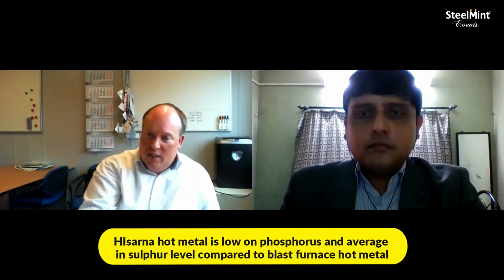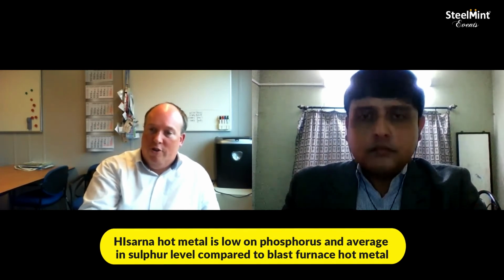Well, the HIsarna process as such supplies a hot metal that is not dissimilar to a blast furnace hot metal. It's got the main components in there, but it's slightly lower in carbon, about 4%. It's got virtually no silicon. It is low in phosphorus, and depending on the coal you use, you get an average to maybe a little bit high sulfur level. Now, the sulfur removal as such is technically not a big problem because steel desulfurization and also hot metal desulfurization are very common processes. So we believe that that is a problem that can be solved.